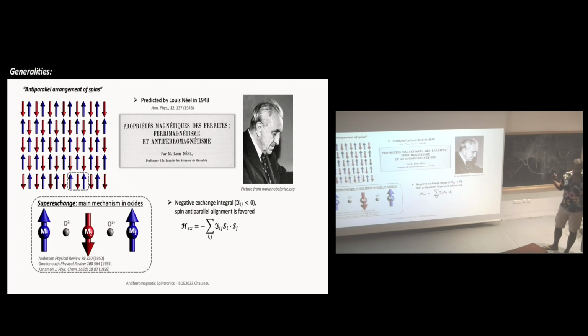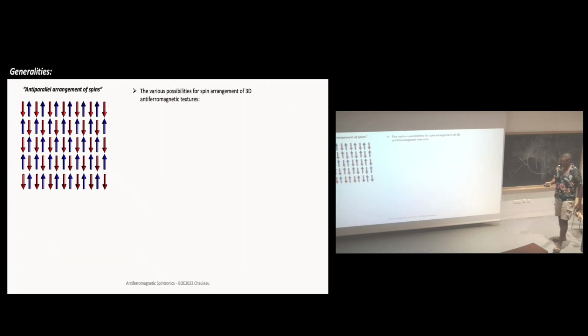And as we are dealing with oxides, and as you've already been told during the talk of Sophie de Brémond, the main mechanism is superexchange, where the exchange is mediated through the p orbitals of the oxygen between the two neighboring magnetic ions. So that's the main mechanism. And as I said, in real life, most magnetic oxides are antiferromagnets. So it's quite interesting. But of course, as you can see here, the magnetic texture could be quite simple.